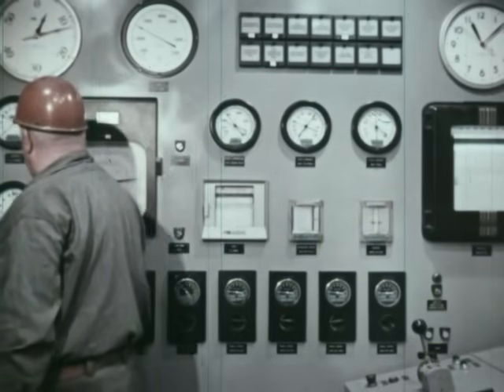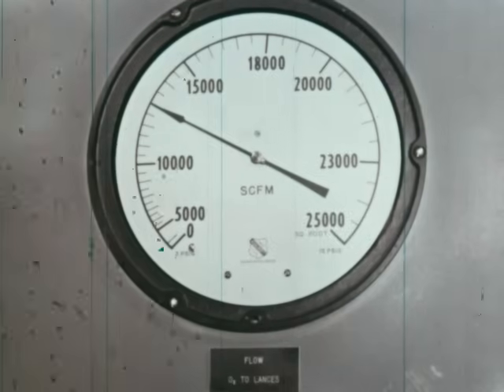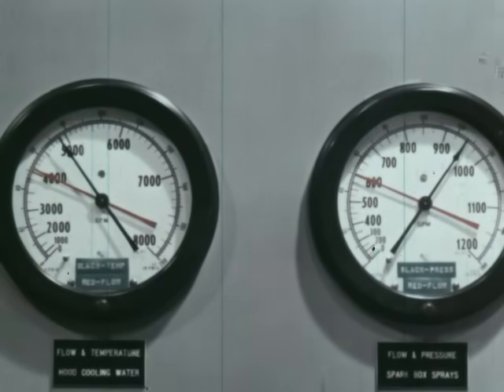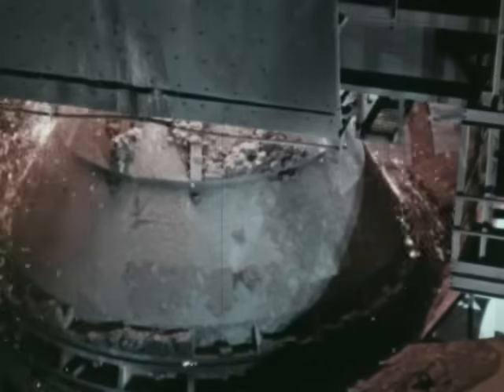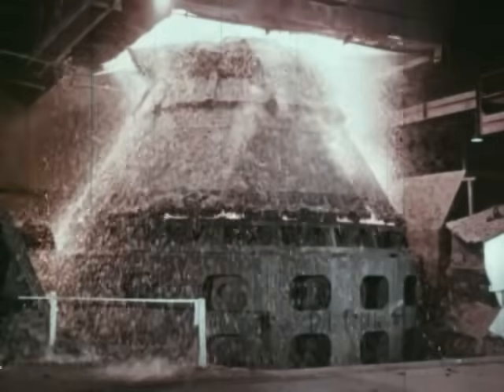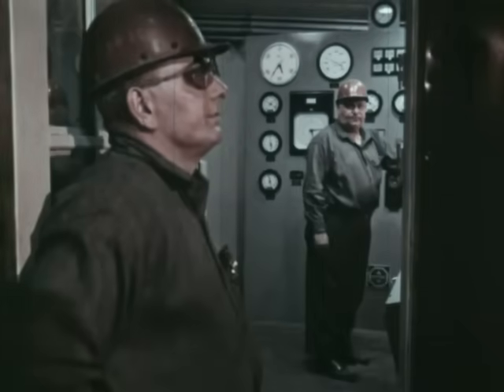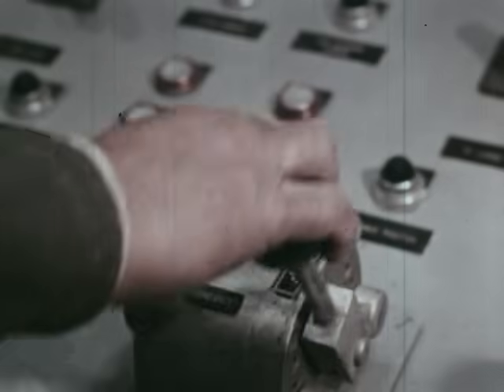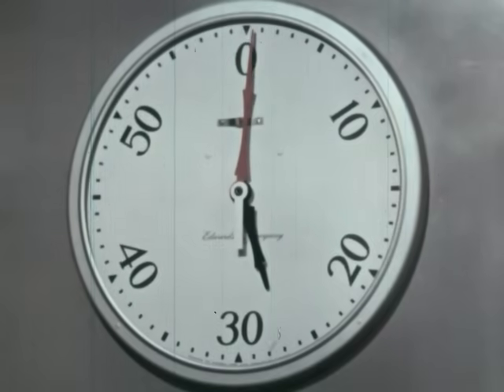During the course of the blow, the operator checks instruments that record the progress. The oxygen flow rate, the temperature of the cooling water. After 26 minutes, the blow comes to the end point. The flame changes intensity and color, signaling that oxidation has been completed. 27 minutes after the blow started, the oxygen is cut off and the lance is withdrawn.